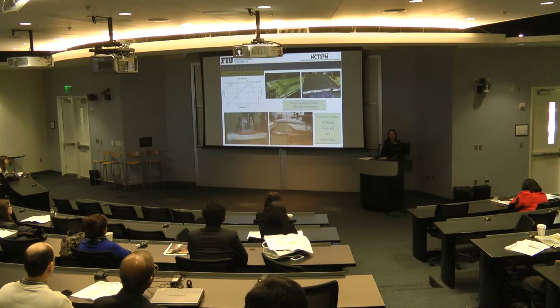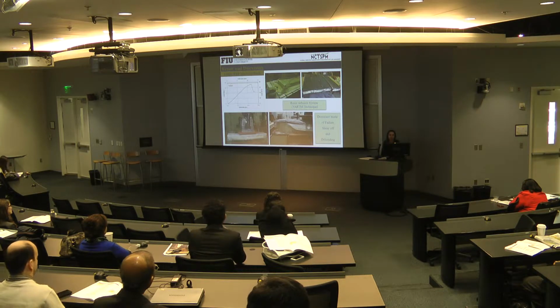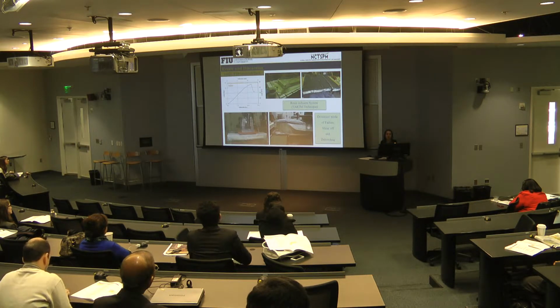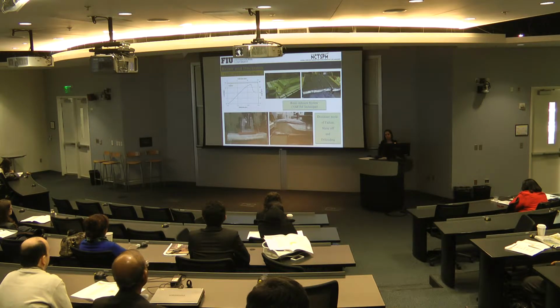For the last specimen, we use the hybrid sections. For building and casting this specimen, we use a kind of vacuum bagging system. There were 6 specimens tested in this way. The difference between these specimens was the number of layers of laminate that we used, both in flexural and in shear. And there were some differences in the thickness of the slab. You usually see a slab on the top. One of them was 3/4 inch, the rest were 1/2 inch.